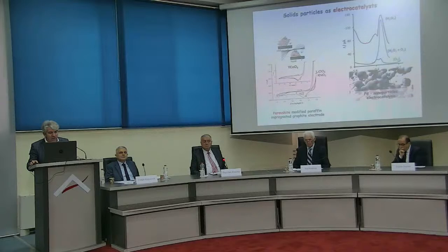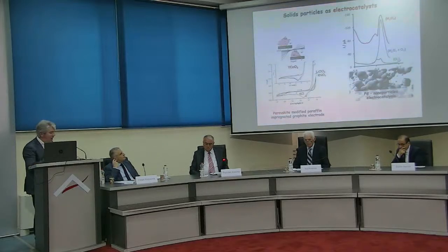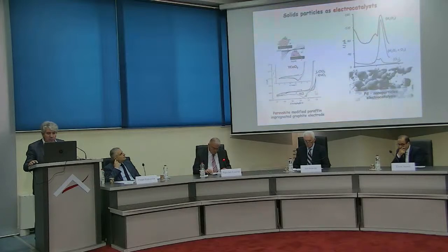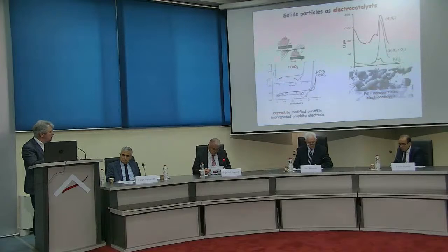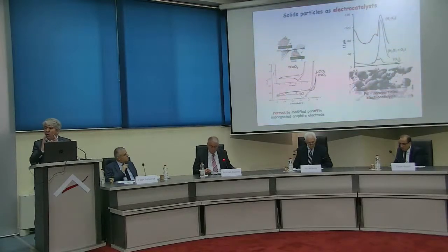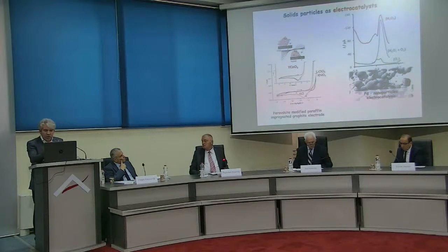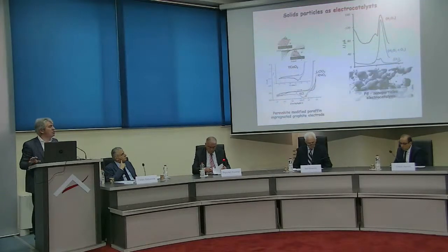We can oxidize chloride ions at a lower potential, and then we have something to reduce, some sort of electrochemically created electrosorption mechanism, electrochemically created sort of chemisorption or physisorption of chlorides, or sort of chemical bond with the perovskite, which enables later to reduce that bond and to receive electrochemical response.